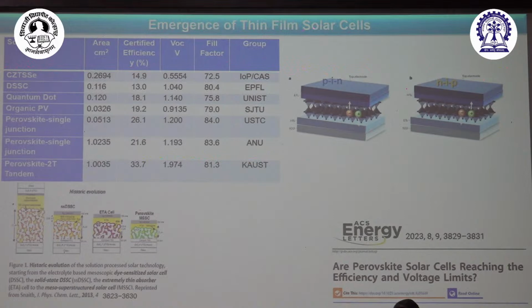So this is where the problem is. If you start making larger panels, this is going to drop down further. Silicon solar cell, I said 28%. That's about 1 centimeter square. But if you make it large panels, they go anywhere from 15 to 20%. So why the efficiency is important? Why it is important?